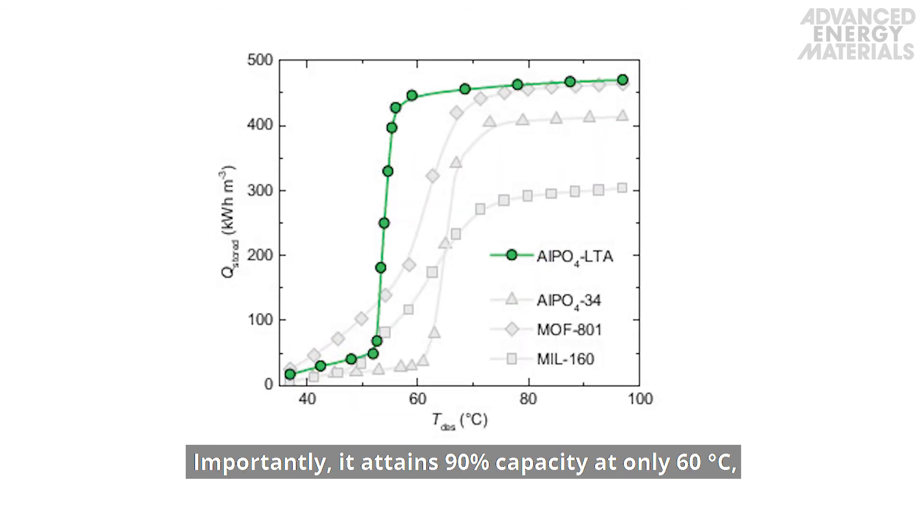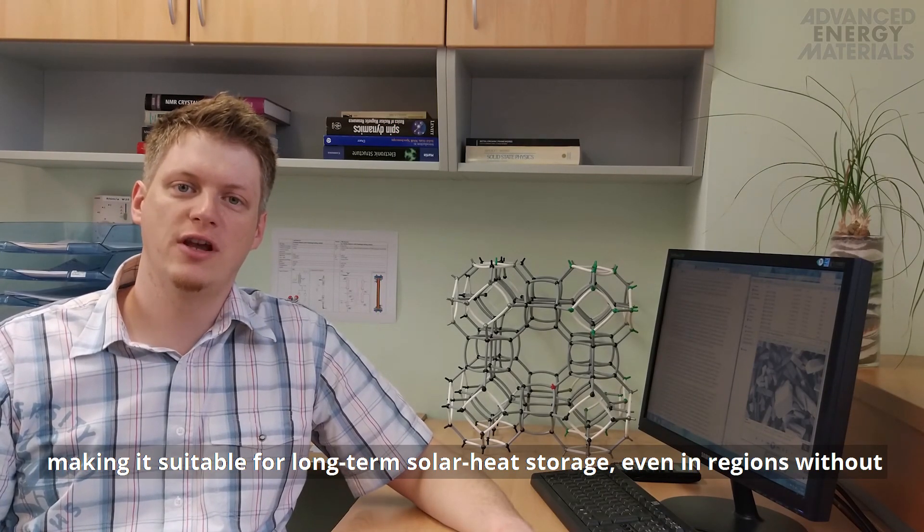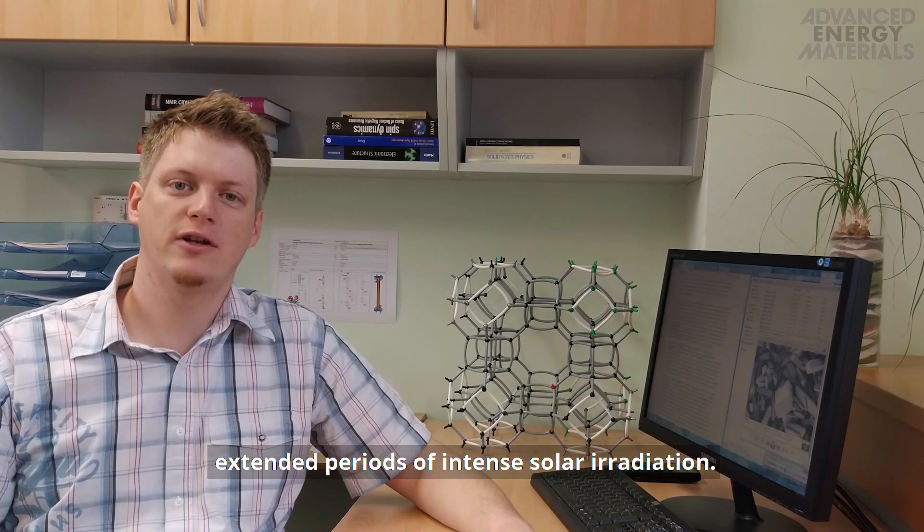Importantly, it attains 90 percent capacity at only 60 degrees Celsius, making it suitable for long-term solar heat storage even in regions without extended periods of intense solar irradiation.